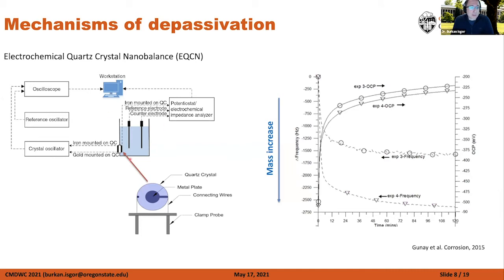So we created this EQCN cell where we put a quartz crystal with a pure iron coating and expose it to a pore solution, or simulated pore solution, and we first passivated it. When you passivate, you can see the OCP, open circuit potential, going in the passive direction. You can also see the frequency of the quartz crystal decreasing, which is an indication that a mass gain is occurring, and this is an indication of passive film formation.